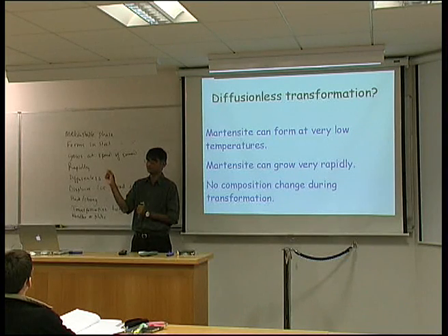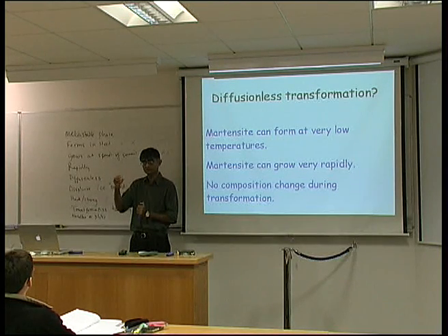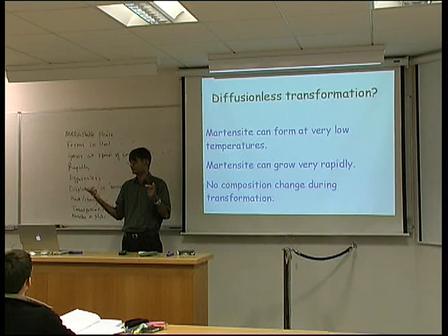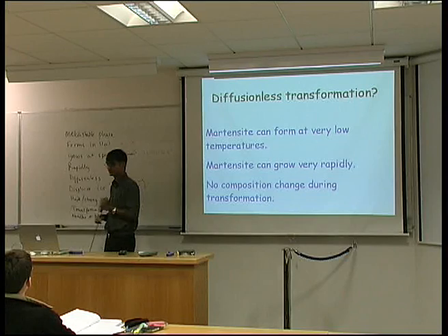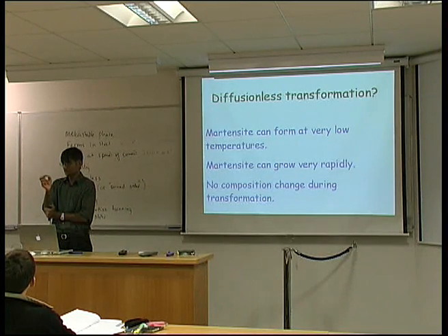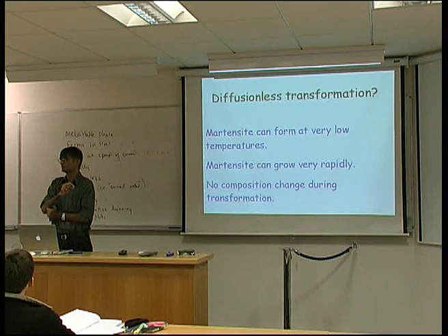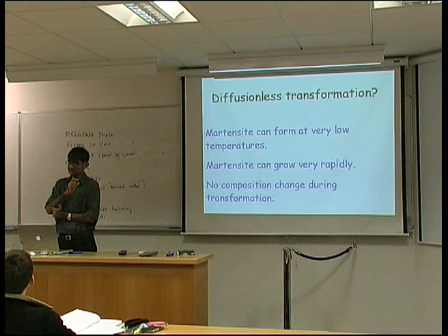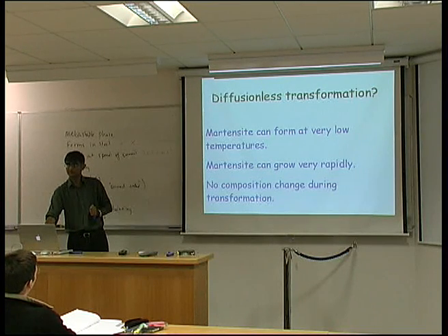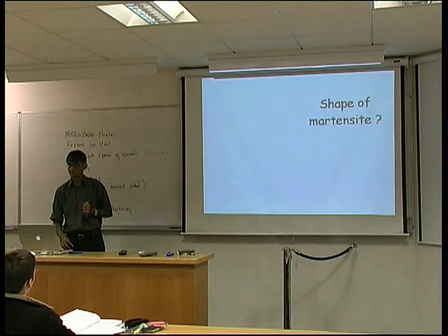Okay. You know, time of flight mass spectrometry. You pull out the atoms, you find out how long they take to fly between two points, and therefore you identify what they are. So on the highest resolution experiment that we can do, which is an individual atom, the transformation is truly diffusionless. Okay, so that's the evidence for diffusionless transformation.